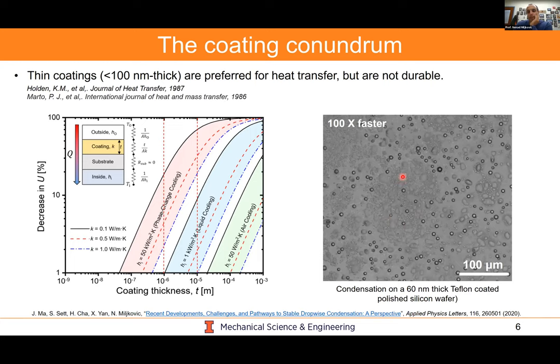And the reason this thinness is particularly important is if you were to plot the decrease in your overall heat transfer coefficient of whatever heat exchange application you're using as a function of the coating thickness, you could see that as your coating thickness increases, for the actual phase change heat transfer application, you could have a decrease in your overall conductance approaching 10 to 50%. Meanwhile, if you were to go to lower efficiency heat transfer applications, such as liquid cooling or air cooling, this is not as much of a constraint.